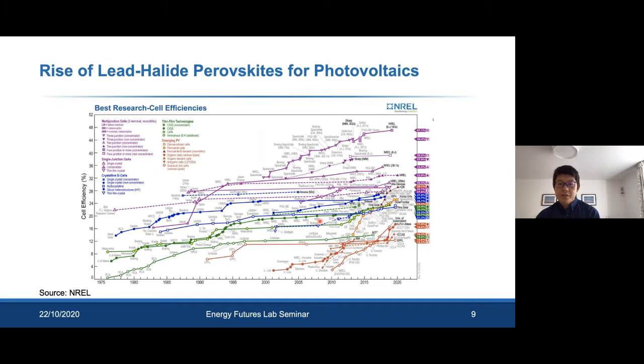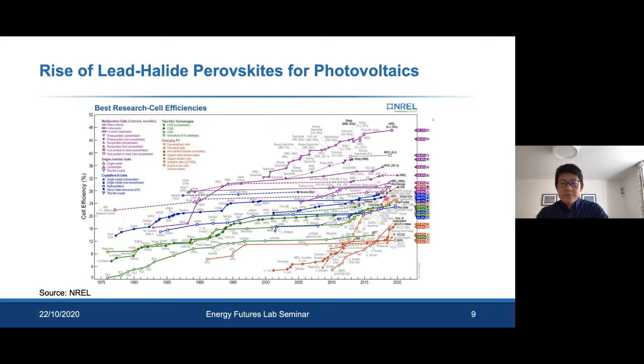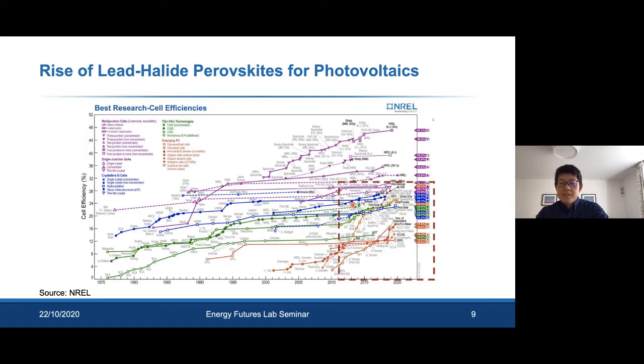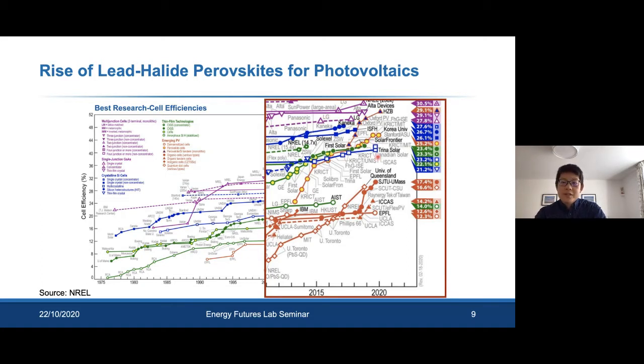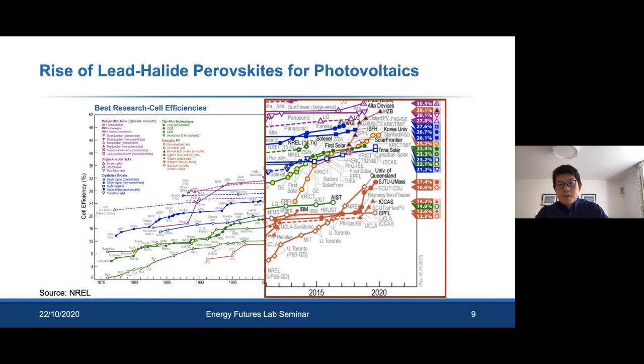There are many photovoltaic technologies. The NREL chart highlights their development over time. The most widely used material for outdoor solar cells is crystalline silicon, developed over four decades, but silicon's challenges have motivated groups worldwide to identify alternatives. One of the fastest-developing technologies is lead halide perovskite solar cells. First reported in 2009, by 2019 they reached 25% efficiency — more efficient than multi-crystalline silicon and nearly as efficient as monocrystalline silicon — achieved in just one decade compared to silicon's four.